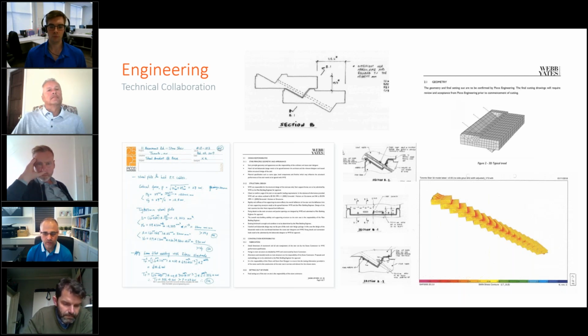Webb Yates took the lead with modeling and stress analysis, and it was an iterative process to achieve optimization. It was tricky to balance the design considerations and the required performance. We did tweak the overlap of the treads a bit to ensure continuity of the strand and shear key geometry, but we're setting a high bar for our fabricators with respect to tooling detail of the treads.